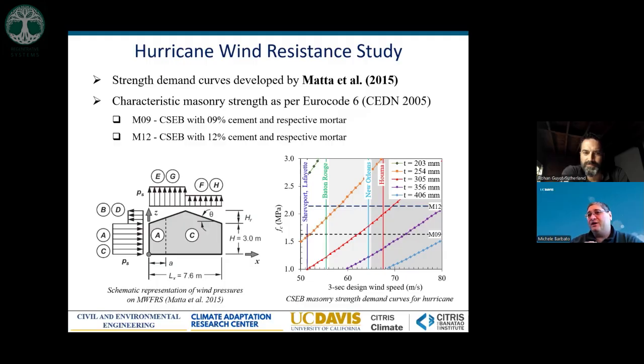On the horizontal axis, you have the 3-second design wind speed that is used in ASCE 7 to identify the loads that are applied to the houses and buildings that are subjected to tropical storm wind types. The vertical axis reports the mechanical strength of the brick, and the horizontal dashed lines with the indication of M12 and M09 indicate the amount of cement and the corresponding strength for the different blocks. So everything that is below that line is a requirement of strength that is lower than the actual strength for the blocks that were produced with 9% and 12% cement.